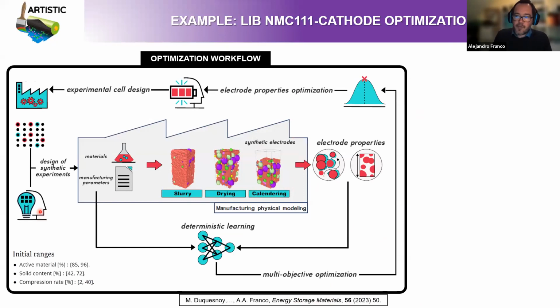We have actually performed a design of synthetic experiments. That means that we are performing simulations by using the physics-based modeling framework of the manufacturing process of NMC 111 electrodes, by simulating the slurry, drying, and calendering for different ranges of formulations, solid contents, and compression degrees. So here we are playing with the formulation, the solid content in the slurry, and with the calendering degree in the calendering step, by keeping constant the conditions for the drying step.